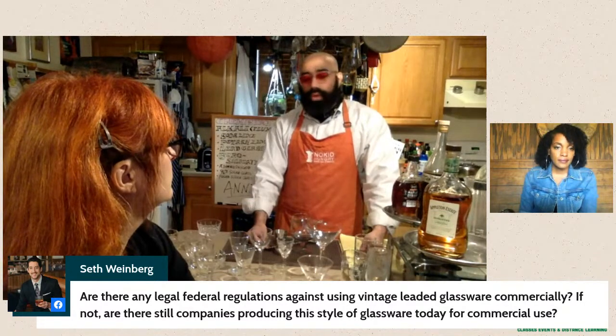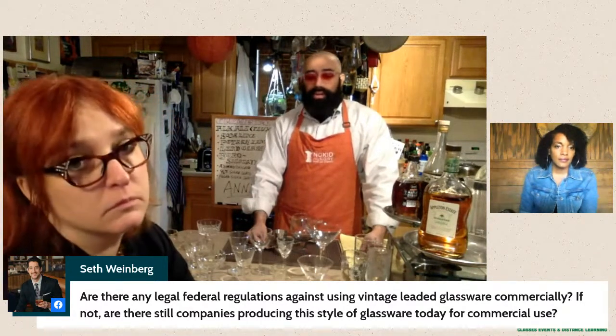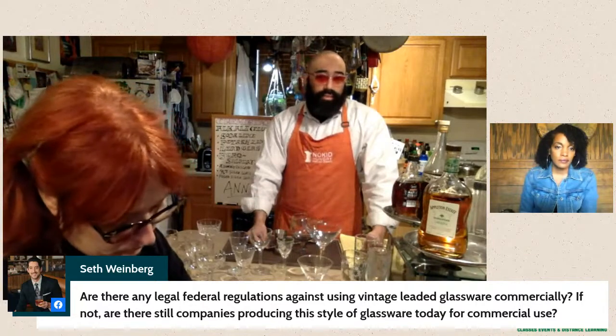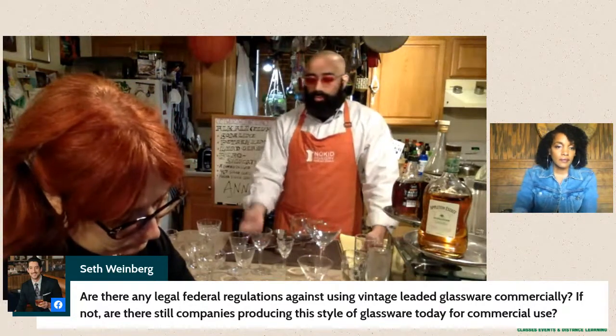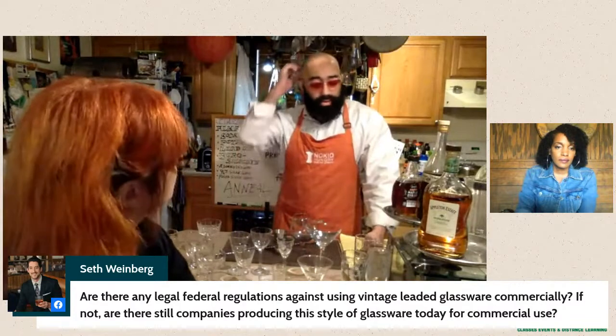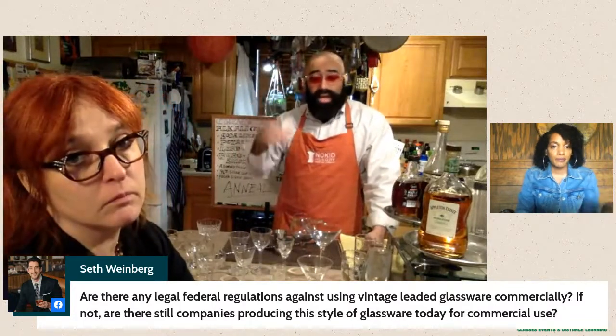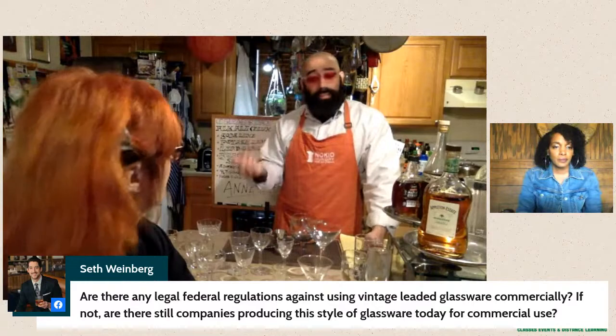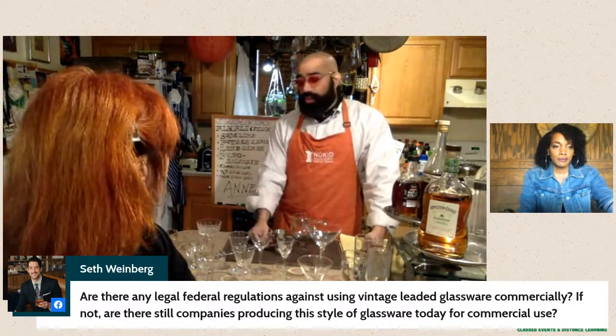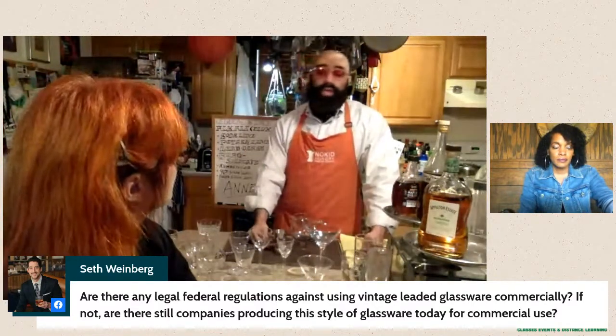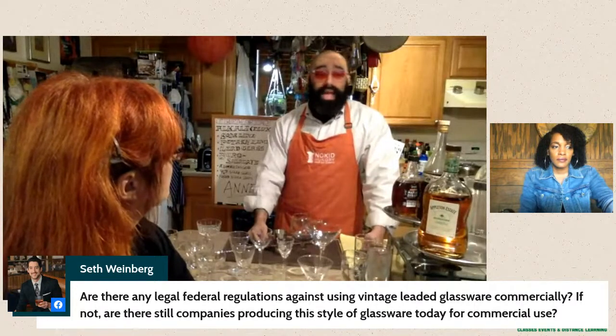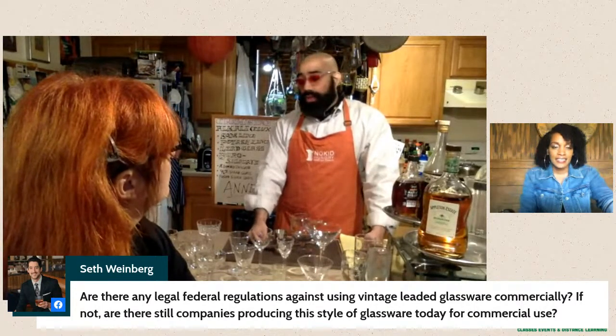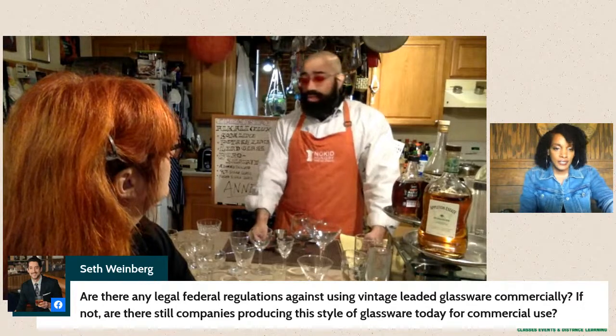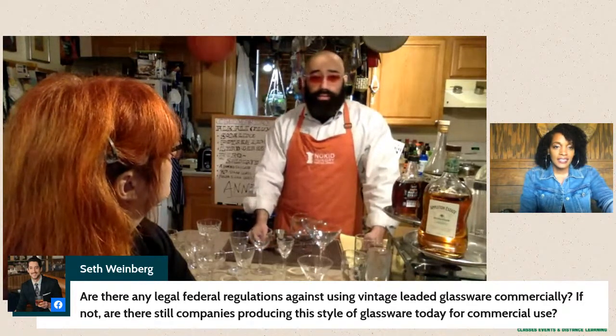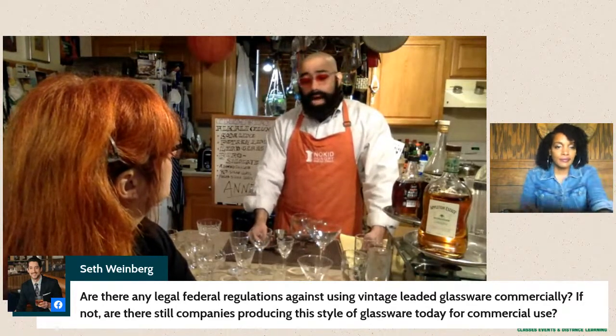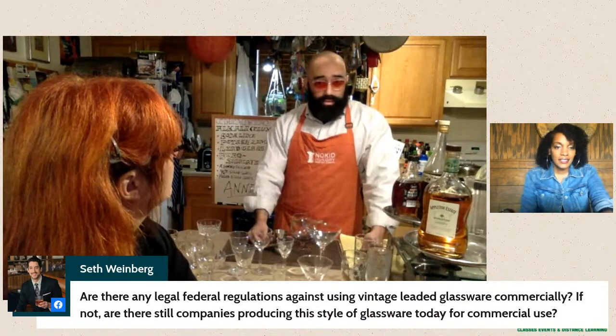You maybe want to avoid using that high amount of lead, because you're kind of asking for trouble at that point, because by the sheer weight of it, it's like, wow, this must have a lot of lead content, and the content does influence how much can leach out. Another thing that influences how much can leach out is what you're putting in it and for how long. So using a lead decanter or sipping a glass of red wine out of a crystal glass doesn't really expose you to very much lead at all.